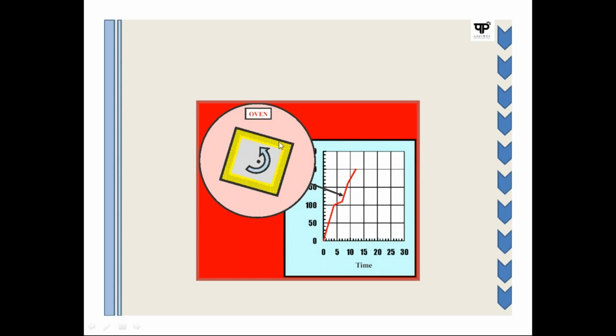So here in this case, the material is completely coated on the inner surface of the mold. Now this is the part where you get the peak, the maximum temperature which you are attaining of the internal air temperature. This is the temperature which you have to find out to get the proper fusion temperature.